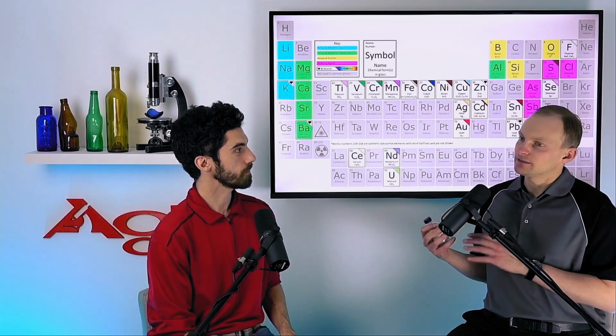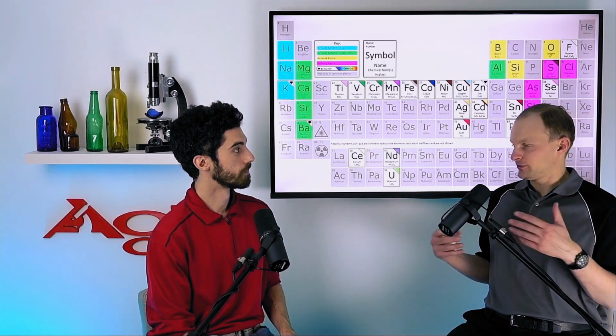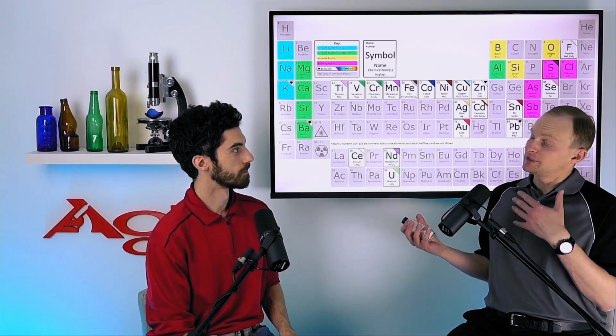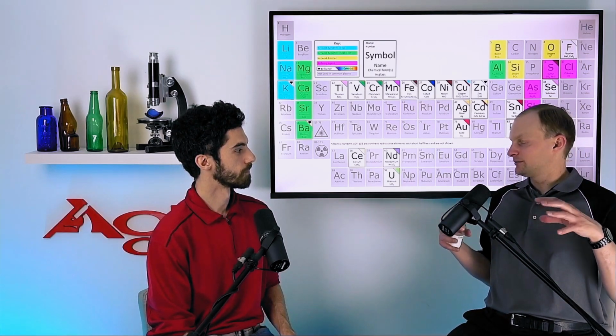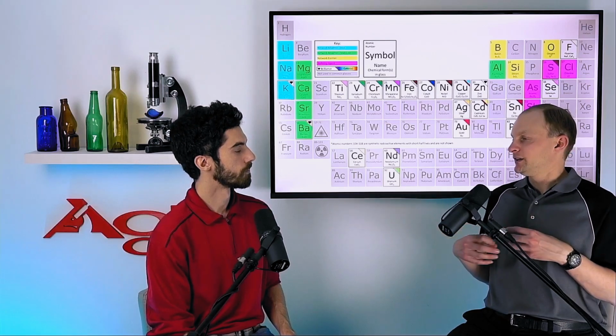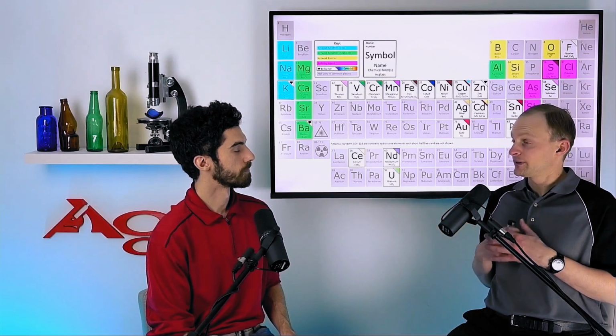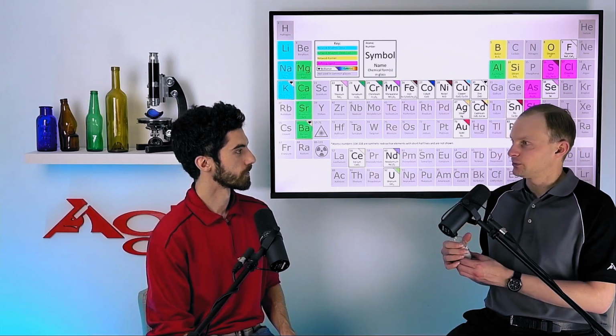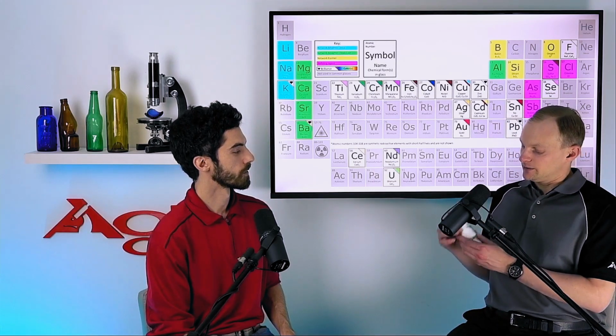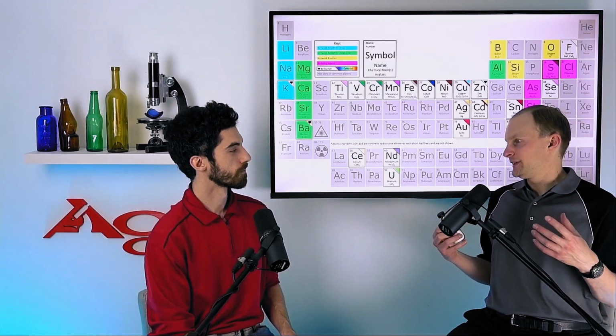In the past, there was also something called potash, which is still a chemical name for potassium carbonate. You can obtain that by burning lots of vegetation, and that will leave residues that are rich in this potassium carbonate. So that can also be used to make glass, but there are some drawbacks and reasons why we don't do that commercially anymore.